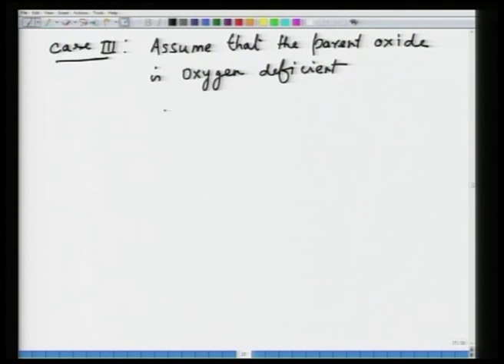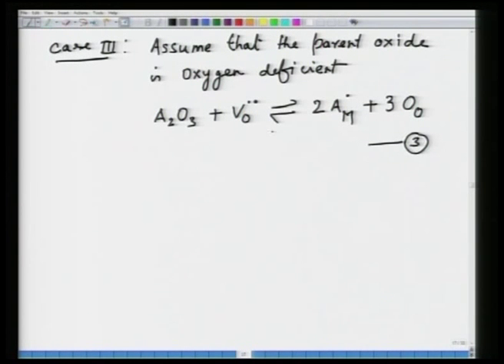So, then what? Now, you have A2O3 going into the MO lattice, plus you had V_O present there. Now, what is going to happen to these V_O? So, both the metals, so you had 2 A's go to M site. Now, what? Since you had 1 oxygen site already vacant and you are going to create 2 for these, all the 3 oxygens occupy oxygen site. So, now what has happened is the oxygen vacancy which was present in the solid to begin with has taken care of 1 extra oxygen. As a result, you do not create any other defect in the material. So, this would be case 3. So, here it is balanced site wise as well as charge wise. You have 2 positive charges on the left and 2 positive charges on the right.